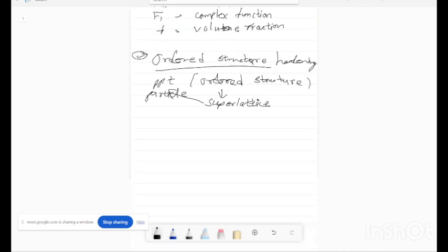So in the interaction between dislocation and the precipitate particle, an antiphase boundary is formed. Antiphase boundary is also formed during solid solution strengthening, and it is also formed during the precipitate and dislocation interaction. Due to the formation of the antiphase boundary, the energy associated with this antiphase boundary results in an increase in the strength of the alloy.